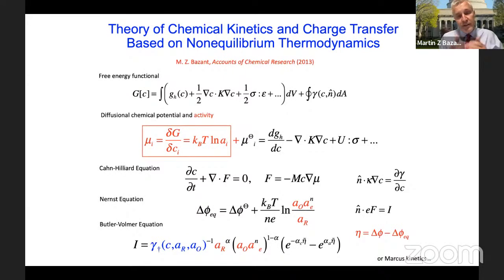And so I like to think of that as mimicking the interfacial tension between phases. So if there's a high concentration and a low concentration phase that are near each other, then where there's a big gradient, that term very conveniently gives you a measure of the energy of that interface.